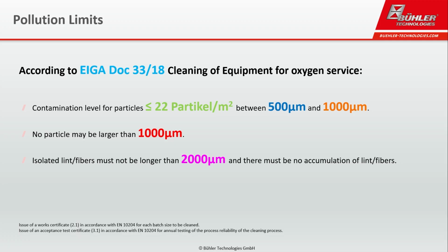The aim of these measures is to control the level of contamination in accordance with the defined specifications. The upper limit for particles between 500 micron and 1000 micron must not exceed 22 particles. In addition, no particle may be longer than 1000 micron. Isolated fluff of fibers must not exceed the length of 2000 microns. These limit values ensure precise and controlled cleanliness, which is crucial for the flawless use of our components.